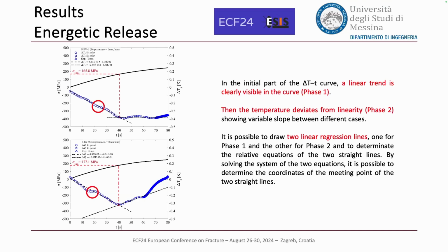So the static test is really influenced by the common issues of composite materials, like the presence of voids or intrinsic defects. So we need a confirmation with the thermographic method, which is an official method. So it can help us in interpreting these results better.